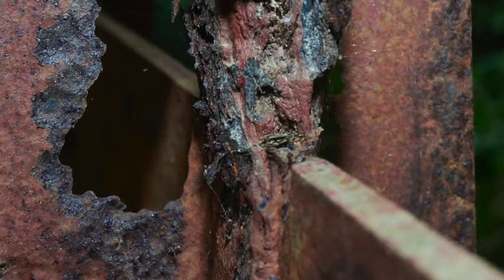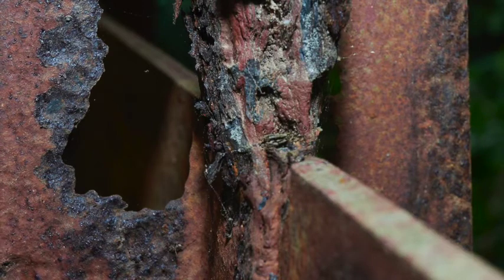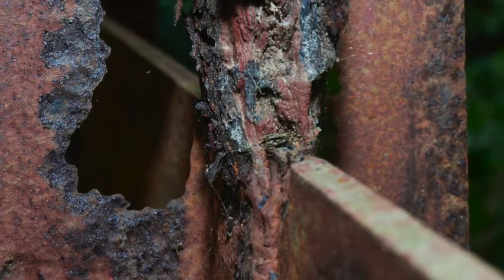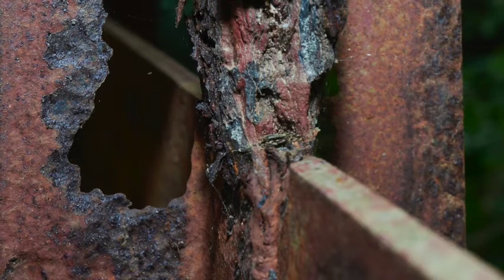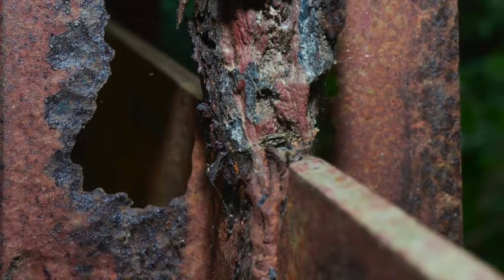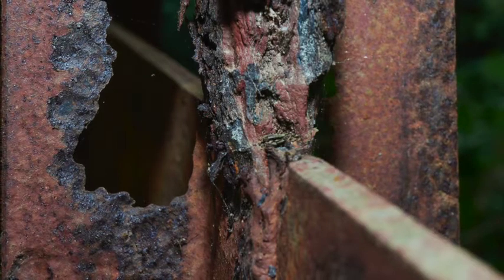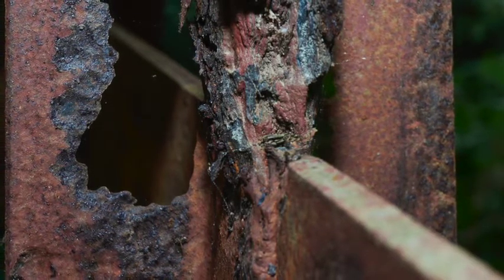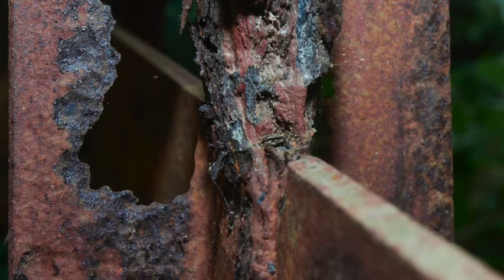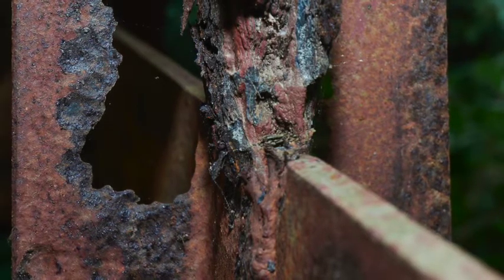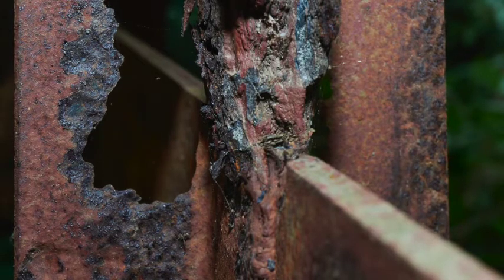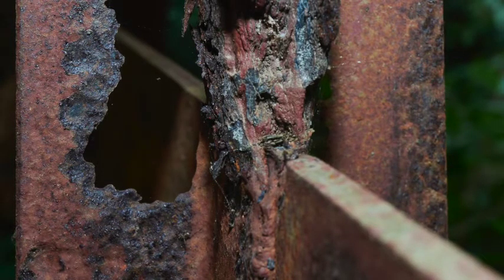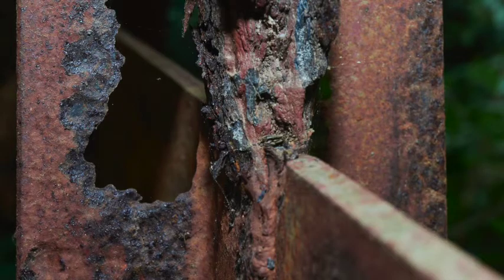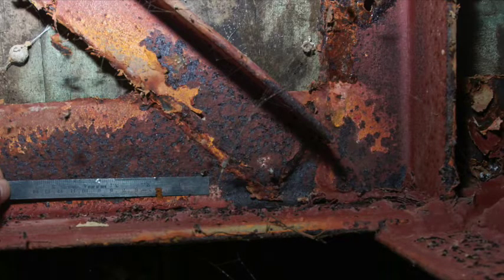Again, for me, there's no way that steel could have been in usable condition 17 years ago when the bridge was built. Assuming the environment's as benign as you describe it, there's severe corrosion beyond pitting to the point where we can see clean through the member. The member, yeah. Now, it's interesting you should say pitting because, again, this is on the underside of the bridge, under the deck, and this appears to be maybe a yellowish... It almost looks like, if I had to say it, someone put orange spray paint on top of the red.